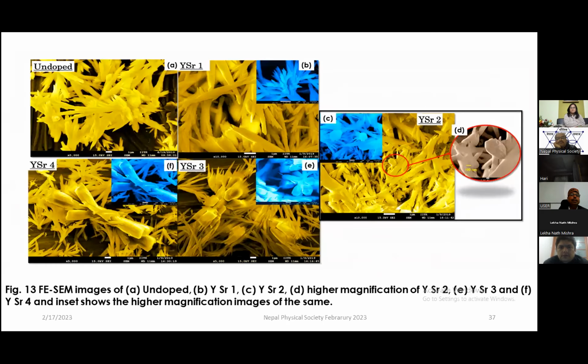After this, we have to go to the FESEM image. In the FESEM image there is a very good tuberose structure, and apart from the tuberose, one can see something more, nanorod-like structures with the tuberose. This is mainly due to the Ostwald ripening process and its orientation mechanism. One can see nanorods popping up over the tuberose. What is shown in this circle has been enlarged on the right hand side.